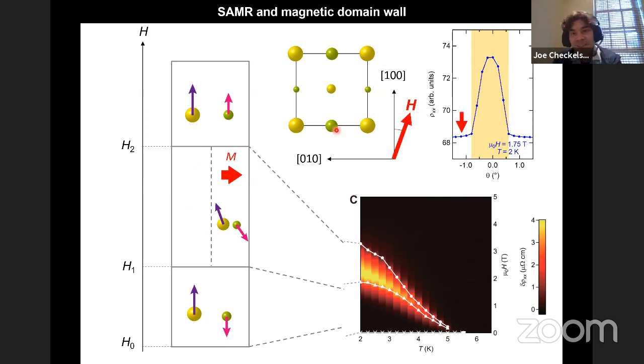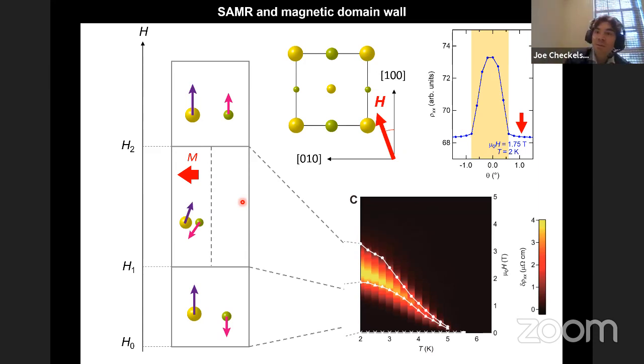However, if I tilt the field just a little bit in one direction, as I go through this transition, I will again go from having spins all this way to spins all this way, but the energy of these two states is no longer the same. And I actually favor one of the magnetic domains. That would also be true if I tilted a little bit the other way. So this series of transitions you go through by having a slightly tilted magnetic field only involves sort of half of the magnetic degrees of freedom.